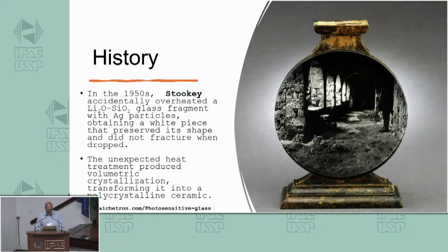And in a hurry, he tried to pick the fragment. He thought that the furnace was destroyed, but actually he was able to get the white piece inside the furnace, let it drop on the ground, and it sounded like a metal. And that informed him that it was interesting, because it didn't break when he dropped it, and he was smart to understand that the piece of glass had crystallized.